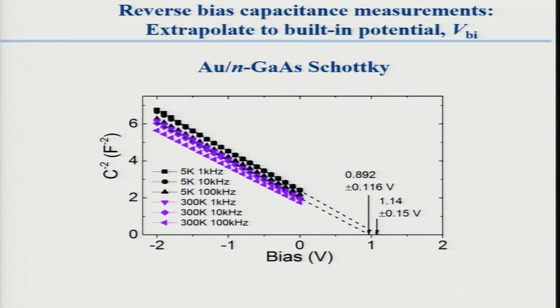There's one thing about these van der Waals junctions, and it's just nature being kind to us. We almost always see nice linear plots with very nice intercepts. So we get V_BI rather convincingly. This is for the gold N-type. This is not a van der Waals junction, but we happen to get it also for a gallium arsenide gold junction. And you can see that at various frequencies and different temperatures, you get an intercept of V_BI here. There's not that much temperature dependence. And you can just read off the intercept.